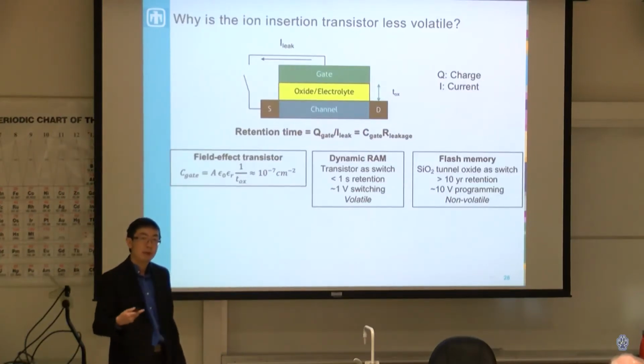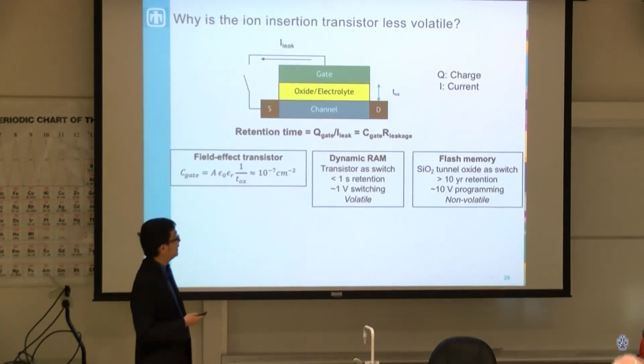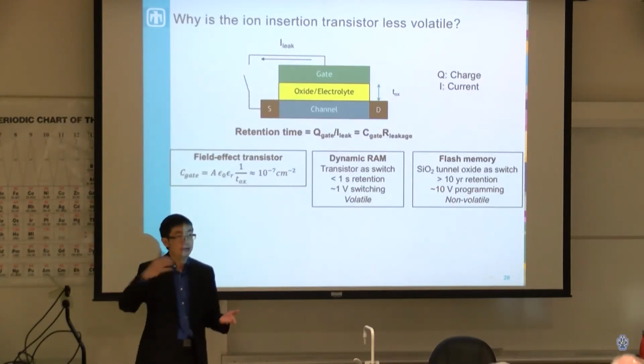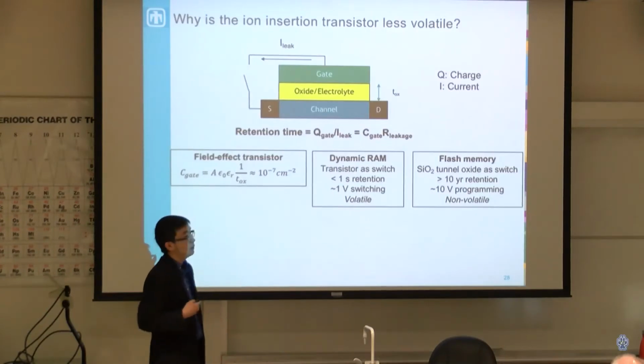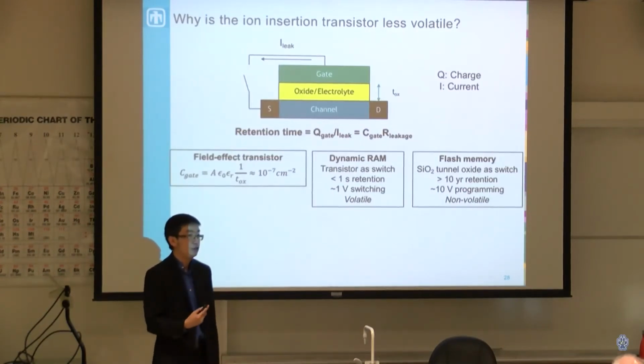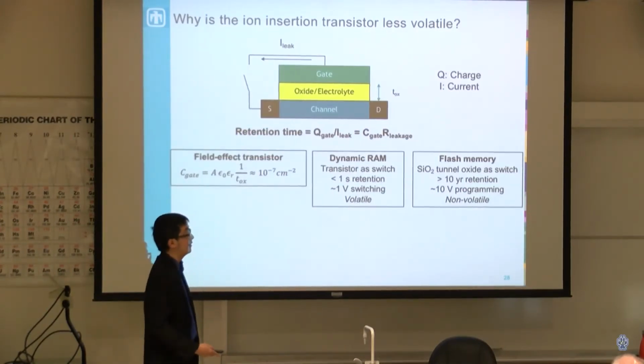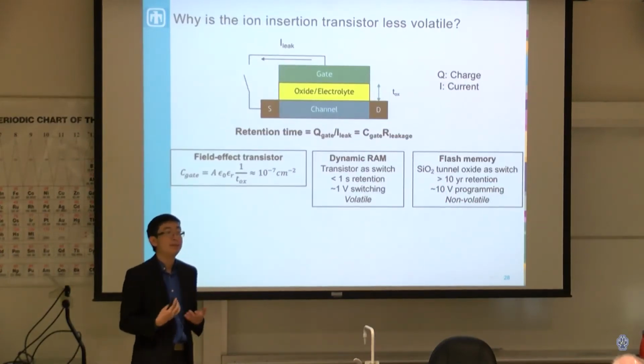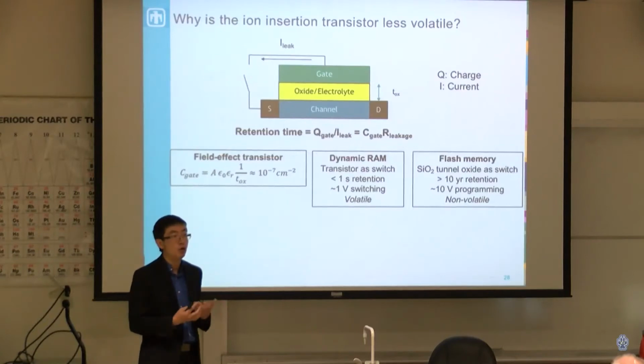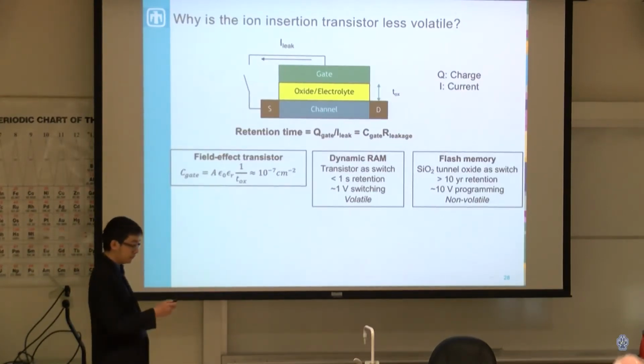And the way that we program flash memory is that we apply over 10 volts of programming voltage in order to tunnel through the oxide, so you can force the electrons to go through the oxide via tunneling. However, this requires a lot of energy, a lot of power, and ultimately limits the lifetime of flash memory to the order of 10 to the 5th to 10 to the 6th cycles.